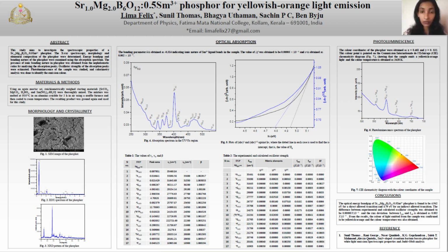The SEM image of the phosphor is given in figure 1, and figure 2 represents the EDX pattern of the sample. Figure 3 depicts the XRD pattern produced from the sample. A total of 30 peaks were observed in this pattern. Figure 4 represents the absorption spectrum of the phosphor. The spectrum highlights 17 peaks in the UV-visible wavelength region.